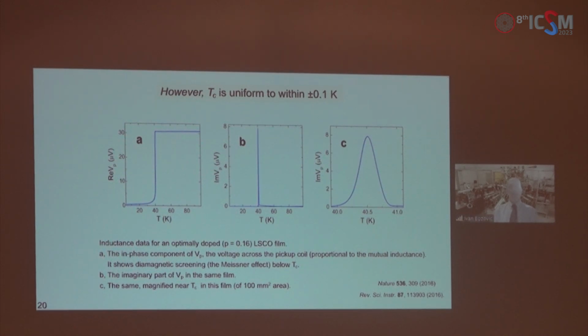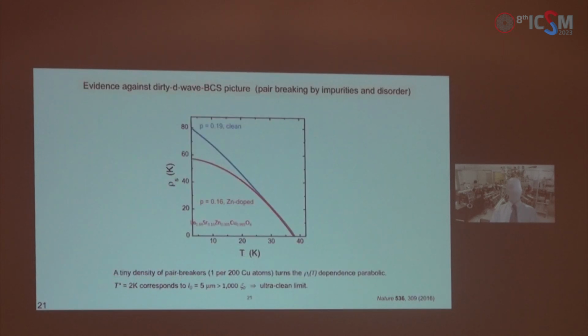This is consistent with what I said earlier about the superfluid density being linear in temperature, as expected in an ultra-clean d-wave superconductor. To double-check this, we deliberately added some chemical disorder by doping strontium cuprate with some zinc. And the temperature dependence changed immediately to a very parabolic one, even with just 0.5% of zinc doping. That means 1 zinc atom per 200 unit cells. So if there is a very small disorder, it screams at you. You cannot just miss it.